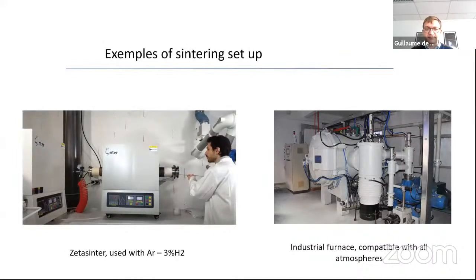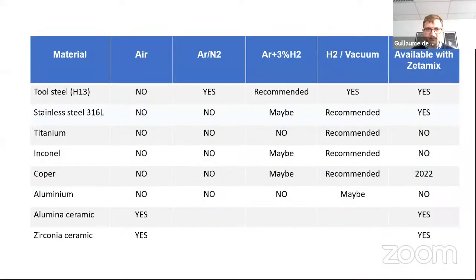To give you an example of the kind of equipment we're talking about, on the left, you have the kind of furnace we offer, which are compatible with neutral gas or argon plus 3% of hydrogen. If we needed more than 3%, we would need to go to more industrial furnaces with a lot of, I would say, specific security equipment to avoid any risk during the manipulation of hydrogen. So that really changes a bit the logic. In one case, you still have something which is relatively desktop, and on the other case, you have something which is really more industrial. And this basically depends on the metal you want to make.